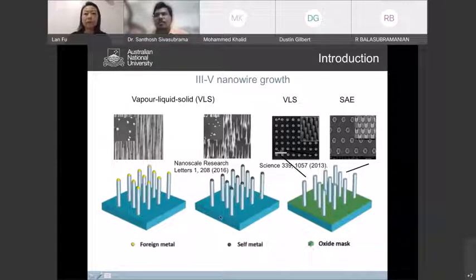So, III-V nanowire growth. Nanowires can be based on different materials: you can base them on silicon or on group II-VI, but for optoelectronics, III-V semiconductors are probably one of the most important materials. And how to make those nanowires? Mainly there are two techniques. One technique is a bit like seeded growth. You put some metal catalyst, you can spray it onto a semiconductor wafer such as gallium arsenide or indium phosphide, and then based on so-called vapor-liquid-solid growth, those little metal nanoparticles act as a catalyst to promote this one-dimensional nanowire growth.